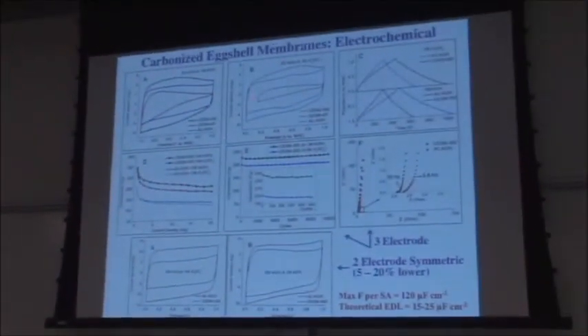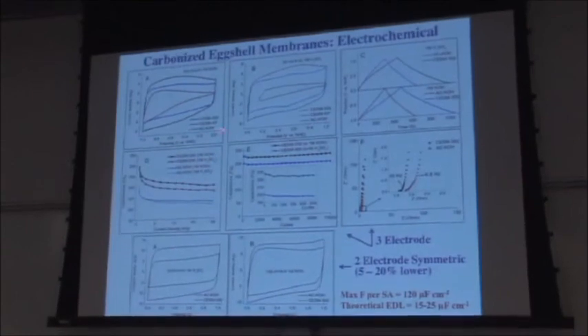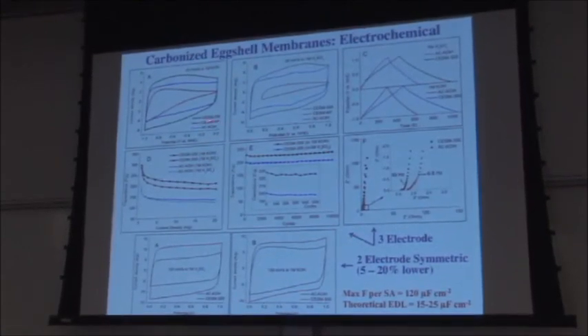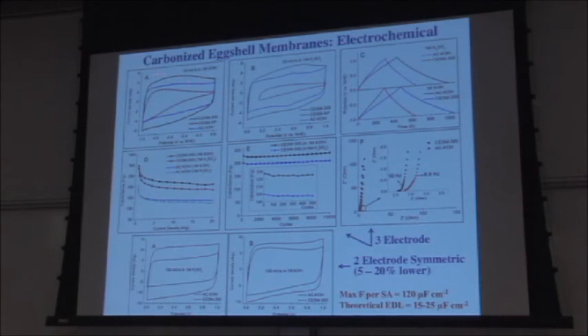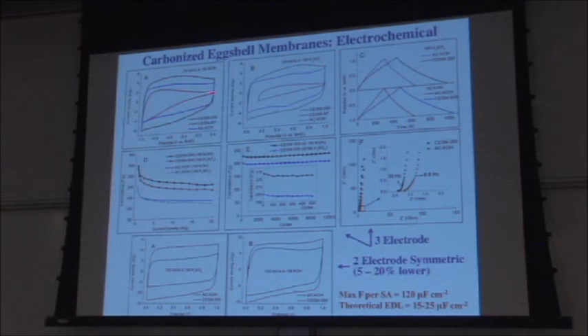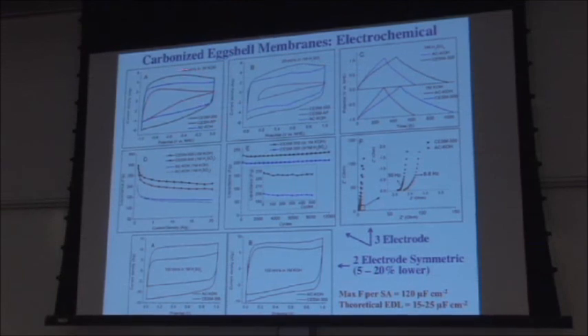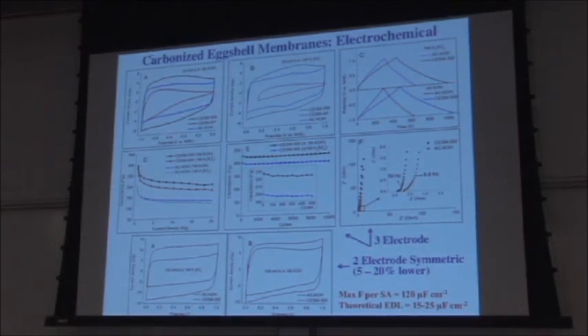So if we looked at the cycling performance, we did both 3-electrode and 2-electrode testing. The CSM, as prepared, has this kind of an ion sieving looking triangular CV curve, but the material activated in KOH and at 300 in air has a box-like structure with very pronounced Faradaic peaks. Especially if you look at the one in KOH, it's quite box-like. The one in 300, very, very nice pronounced Faradaic peaks.